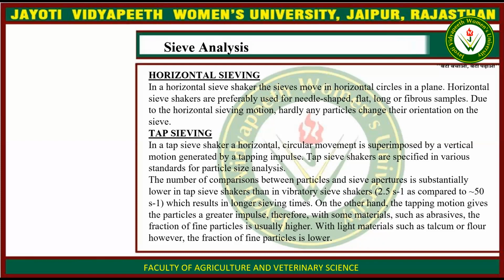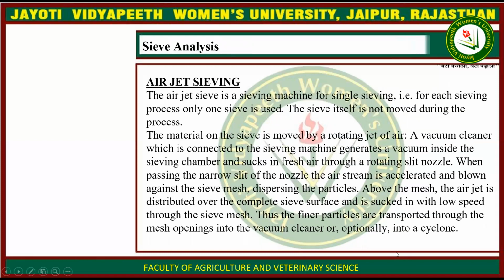On the other hand, the tapping motion gives the particles a greater impulse. Therefore, with some materials such as abrasives, the fraction of fine particles is usually higher. With light materials such as talcum or flour, however, the fraction of fine particles is lower.